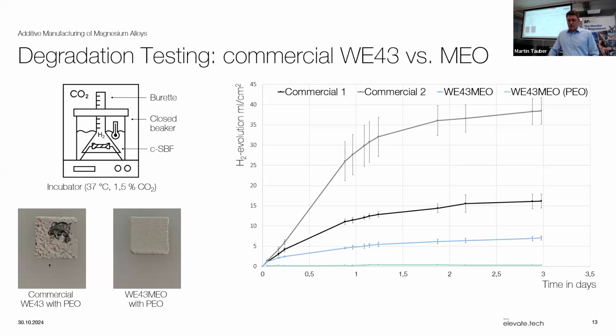And if we take a look at the difference between materials that we produce in-house versus commercially available WE43, and then again looking at the PEO surface converted materials, we see quite a huge impact. One of the tests we do in-house is degradation testing by measuring the H2 evolution. So the material is immersed in a medium where we simulate, in this case, body fluids. And by doing that, we can see how the material probably behaves in the human body. And by collecting the amount of H2 gas, we end up seeing how fast the material degrades compared to other materials.